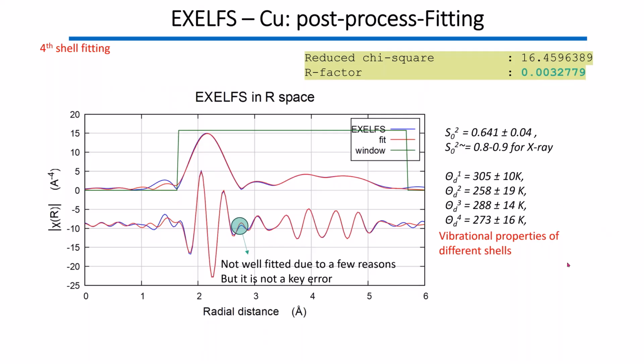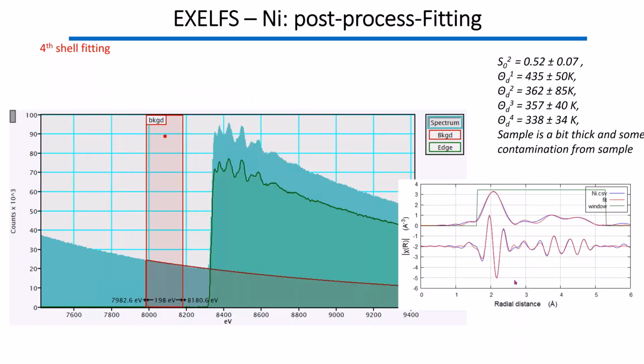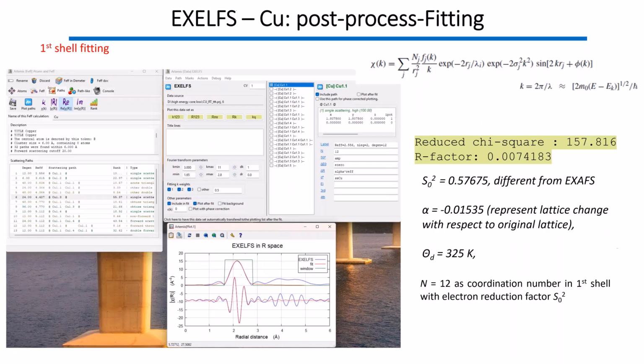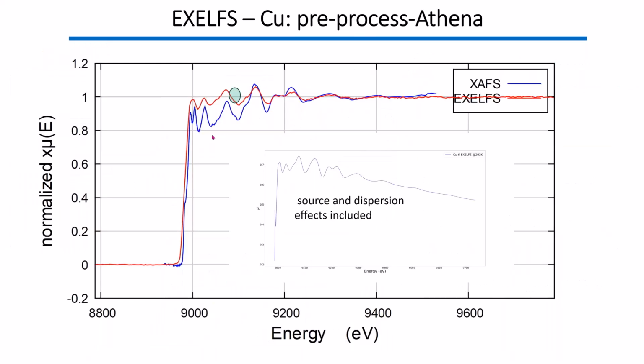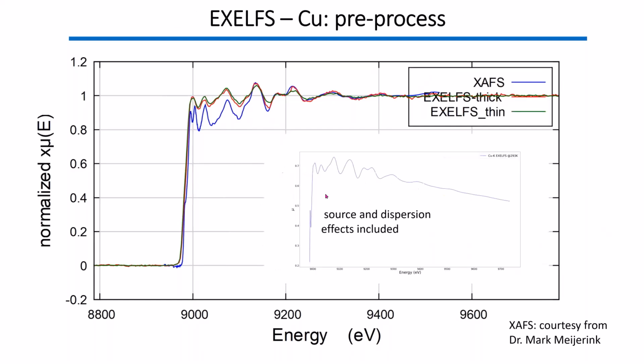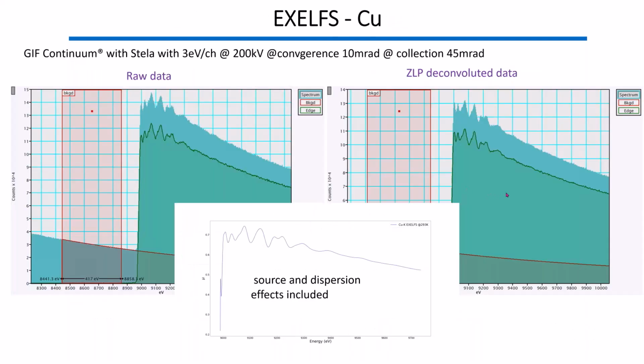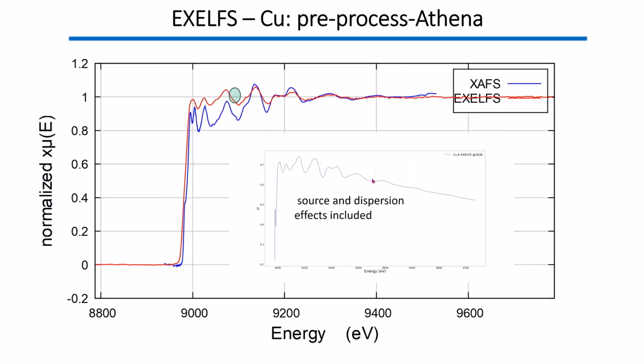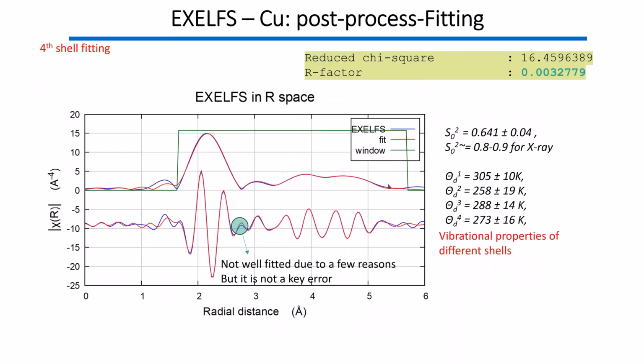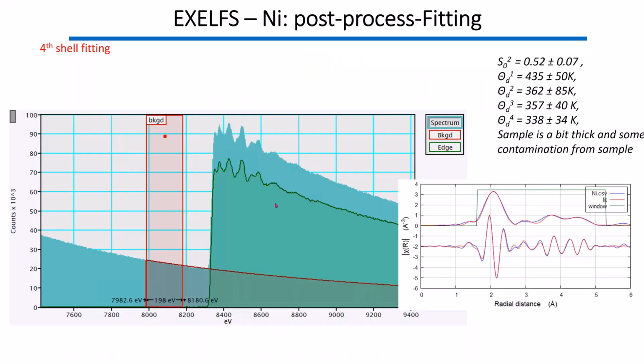We do, and it depends on which spectrum we are talking about. For a typical one like this, we are using roughly 2 nanoamp for the electron beam itself. For the previous data set here, we used in total about 10 minutes. And for the best data set, which we acquired for 20 minutes in total. But we can also go down to something like 1.5 nanoamp for 5 minutes, or 3 minutes, which is more than enough for fitting, basically.